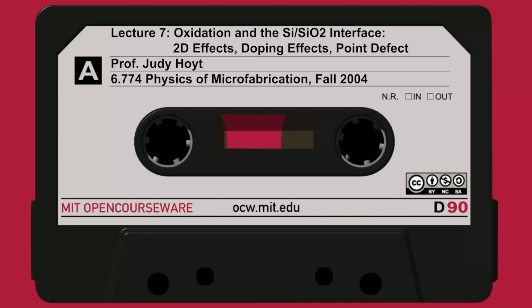The hydrogen can't do anything about this silicon. It's unoxidized. It needs oxygen atoms. So that's why when you do a forming gas anneal, the last step, you can reduce the density of interface states. The fixed charge is a little different. To reduce it, you don't anneal in hydrogen.